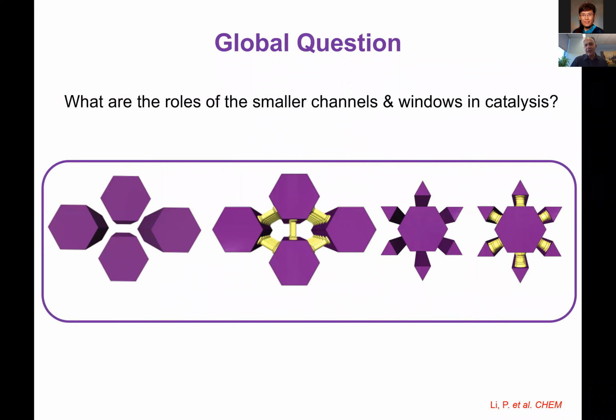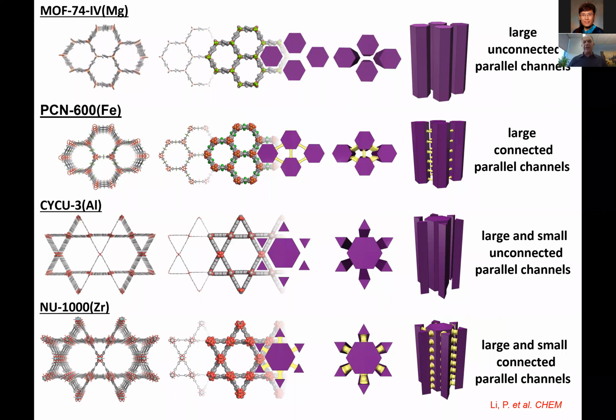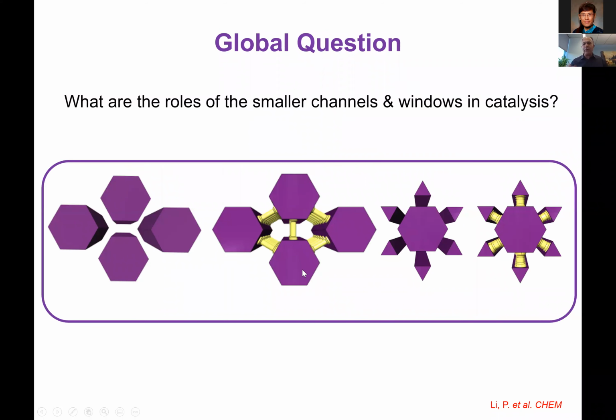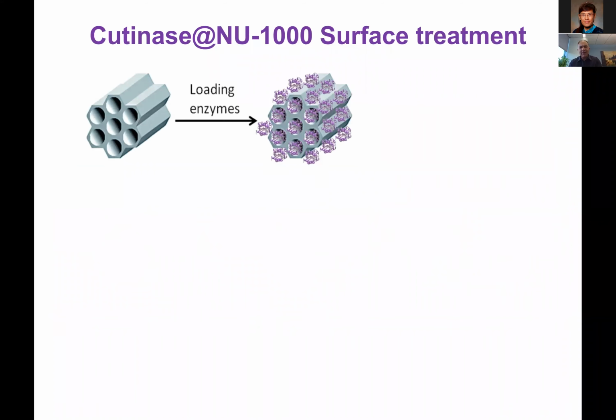The question was here, did we really get lucky? How do we know that our hexagons, triangles is really the optimal material? So what we did, we went and now we made 4 different MOFs. They all have hexagons and they all the same size. Some of them have triangles and they all the same size. And some has the communication between the channels and some don't. So we want to test what's the effect of the triangle with it and without it, and the effect of the communication between the channels with it and without it. We make all the 4 MOFs and we test it.